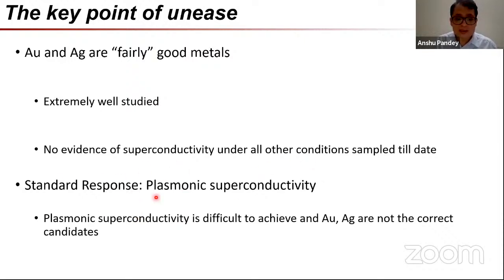The standard response, therefore, which we came up with, because again this is something which has been considered in detail in literature, would be that there's plasmonic superconductivity. But again, this merits several caveats because it is very right to say these are plasmonic materials, so there must be plasmonic superconductivity. But the fact of the matter is, plasmonic superconductivity is ultimately difficult to achieve, and AuAg are not really the right candidates in which we should achieve them. So ultimately, it does lead to a question: what exactly is happening, and how should we think about it?